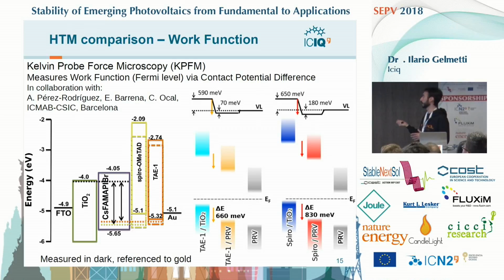So with this technique, we can know the work function, which is the difference between the Fermi level and the local vacuum level of a surface, via a technique called contact potential difference. And we saw a bigger shift when the spiro-OMeTAD is deposited on perovskite rather than on titania, compared with the shift that we observed with the novel molecule when layered on perovskite or when layered on titania. So we observe this bigger shift, and well, this is what we expected.